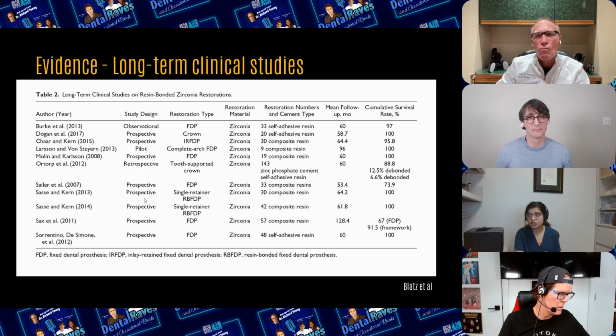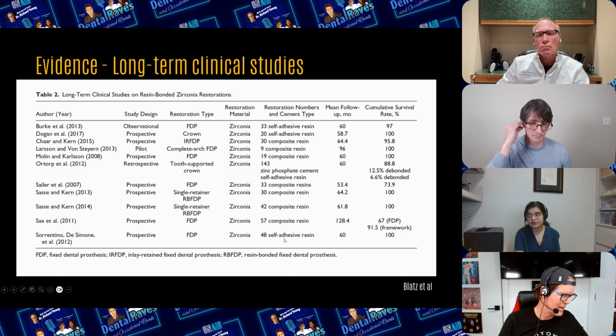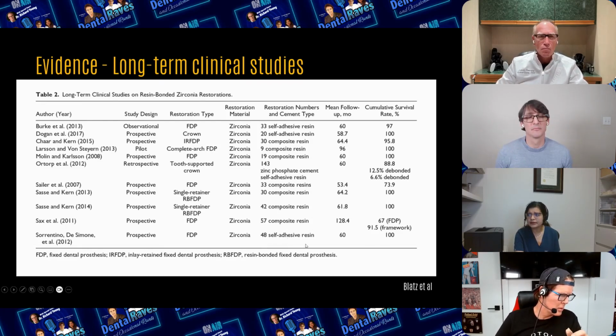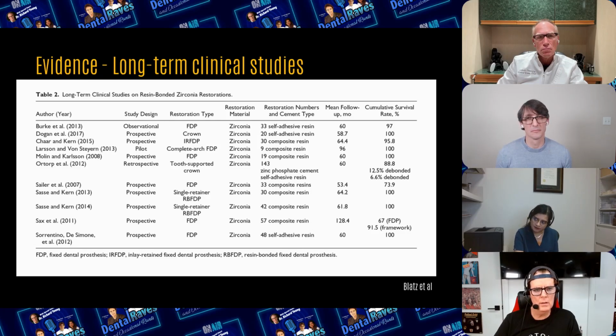But just to get your attention, there have been some prospective studies looking at fixed dental prostheses of zirconia with a composite resin cement and a self-adhesive resin cement. But at the same time, framework fracture was the main mechanical complication observed, and not so much has been investigated for a tooth-supported crown except for one retrospective study that investigated a zinc phosphate cement and self-adhesive resin that was done in 2012 as well. And then out of that study, as you can see from the table, 12.5% debonded, 6.6% also debonded. We have to deep dive into that paper, sorry about that.